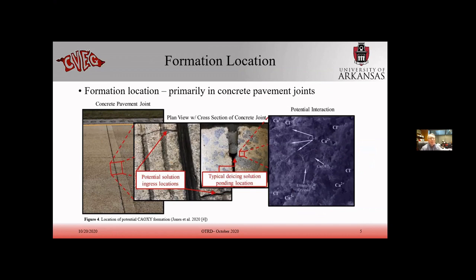So kind of the formation location. Here's a concrete pavement, I think in the Fort Smith area, in the middle western part of Arkansas. You have your concrete joints, and you zoom in on the joint. Here's the tine, so you can see the magnification. It's a tined concrete pavement. They have some cracks that run perpendicular to the joint. Even if the joint is good, some of the de-icing salts can still get into the concrete and pond. If the joint fails, it can pond around the bottom of the joints. Then you have the de-icing salts along with the calcium hydroxide, and that can lead to some of the calcium oxychloride forming.